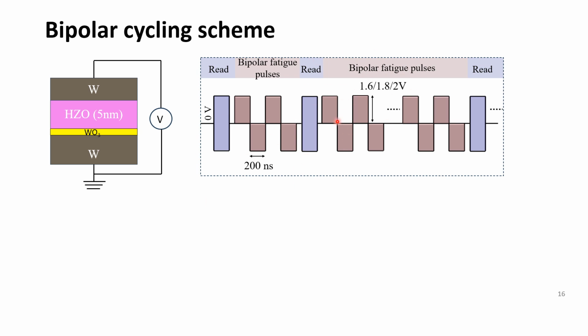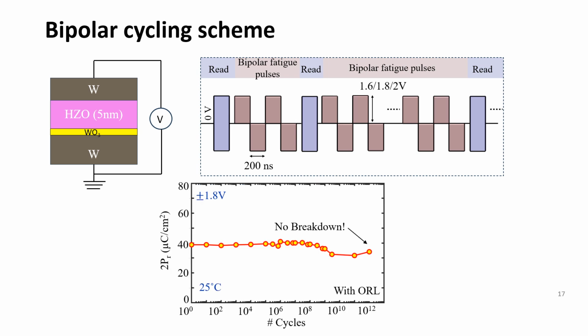So this is the pulse scheme that we have used for measuring the endurance of both the devices. We have used bipolar cycling pulses of 200 nanoseconds each and performed consecutive read operations to measure the 2PR values after a certain number of cycles. And using this pulse scheme, we measured the endurance of the ORL device, which has tungsten oxide, and we could see that this device didn't break at 10 to the power 12.